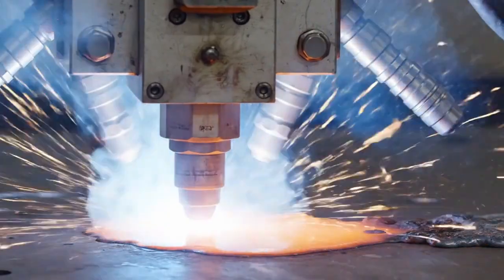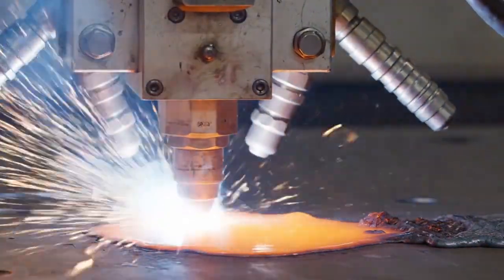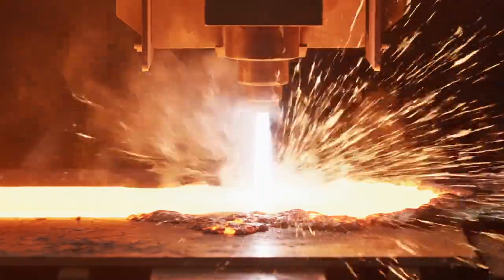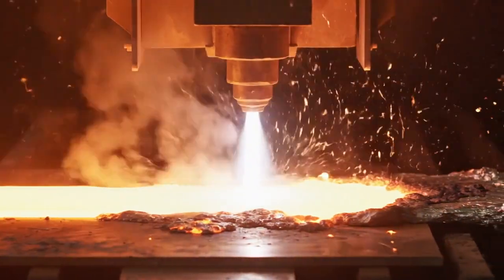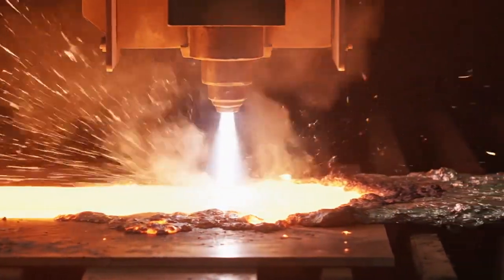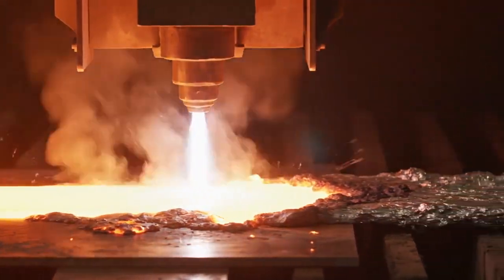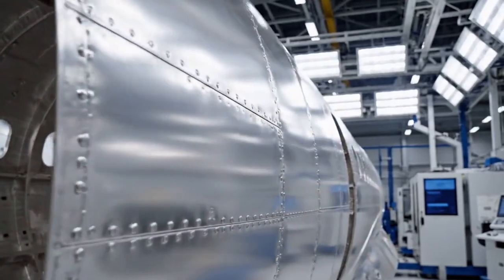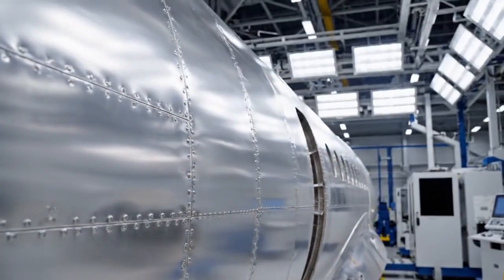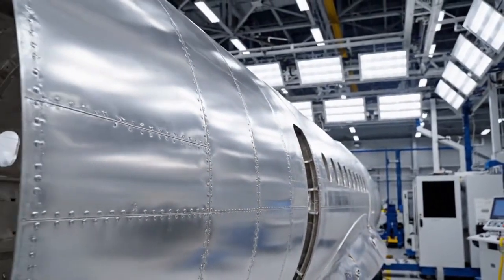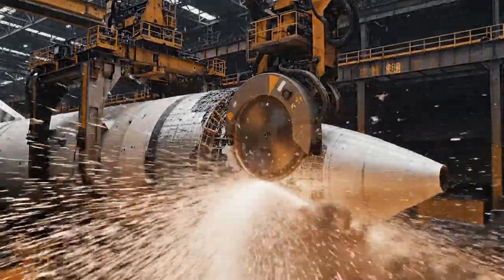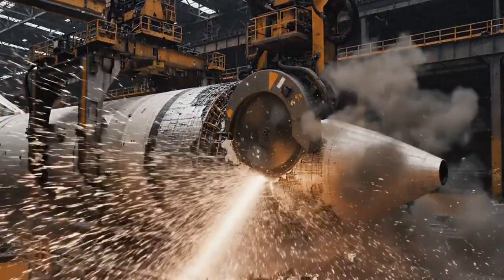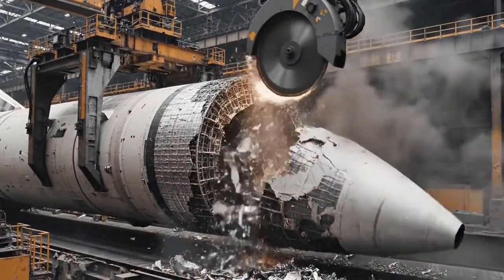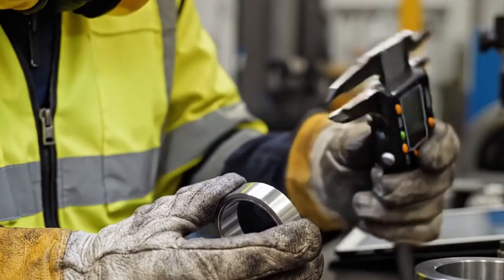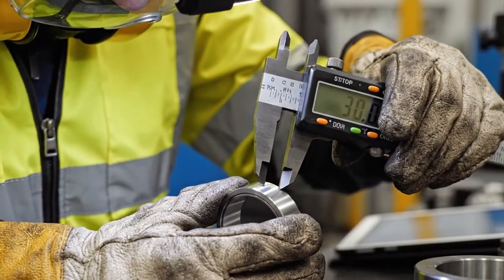A precise mixture of argon and helium is continuously pumped over the melt pool. This invisible atmospheric shield is critical. It displaces ambient oxygen and moisture, preventing the molten aluminum from instantly oxidizing and degrading the structural integrity of the fuselage. If this gas flow is interrupted for even a fraction of a second, the entire multi-million-dollar print must be scrapped. The margin for error is absolute zero.